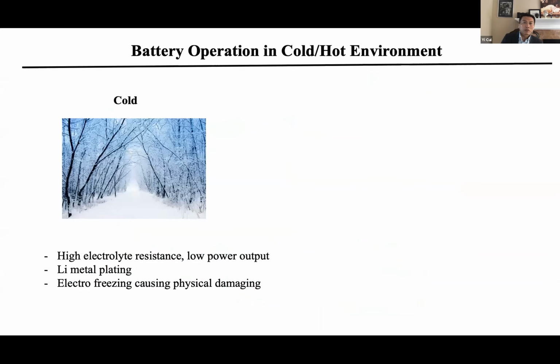So how does the temperature affect its chemistry? We know in cold weather, when the temperature is very low, electrolyte resistance goes up because it's more viscous, and you have low power output. At lower temperature, you want to push lithium into graphite during charging. However, this push-in process becomes slower, and then you can potentially have lithium plating happen more easily. This can cause dendrite formation and potential battery shorting. And also remember there is electrolyte freezing. If you go to a really low temperature, this can cause physical damage.